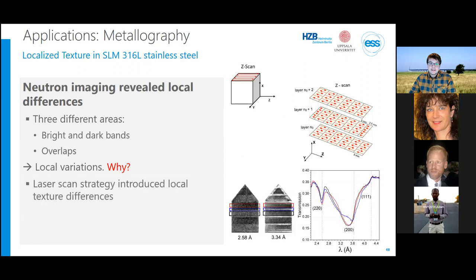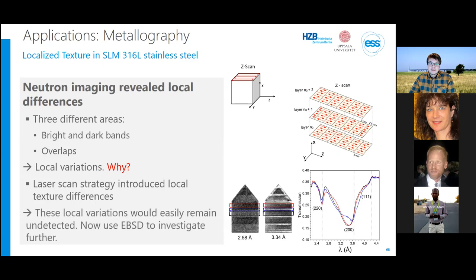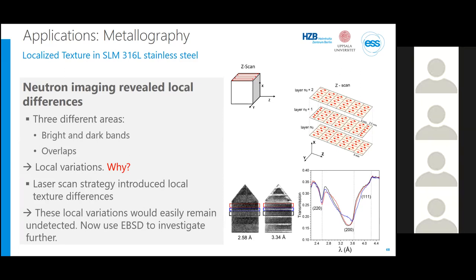Looking into these regions, we can see that there are local textural differences, because these transmission spectra look different in these different regions. From this, it should be obvious that these local variations would easily remain undetected without the use of neutron imaging. We then used EBSD to investigate these regions further. This was totally surprising to the involved colleagues, that we saw these lines at all.